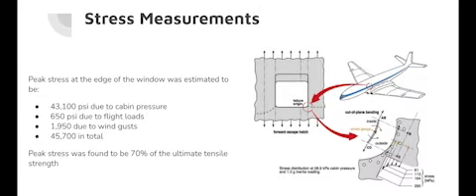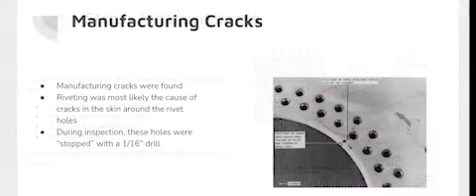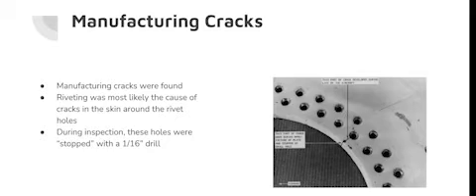Peak stress at the edge of the windows was estimated to be 45,700 psi in total, a combination of 43,100 psi due to cabin pressure, 650 psi due to flight loads, and 1,950 psi due to wind gusts. This peak stress was 70% of the ultimate tensile stress of the material. The Royal Aerospace Establishment found fatigue crack growth from a rivet hole at the low-drag fiberglass forward aperture, which had caused the catastrophic breakup of the aircraft at high altitude.